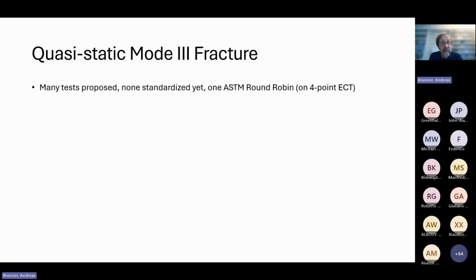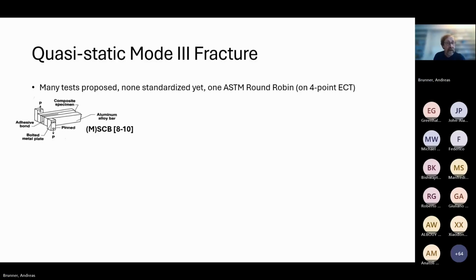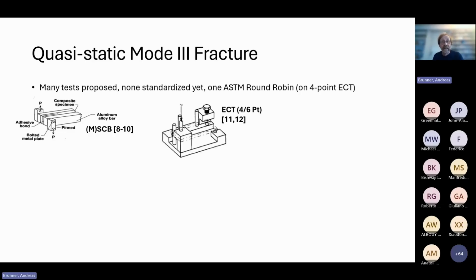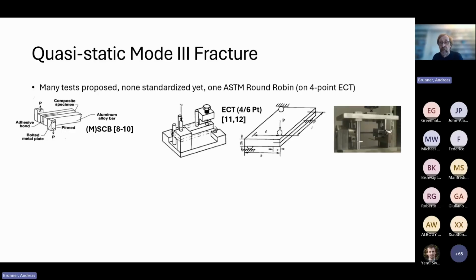Now for quasi-static mode 3, it has already been said as well that there's no standard. There was an ASTM round robin performed in the early 1990s, which used the 4-point edge crack torsion test, but this never led to standardization, and no one has picked up that as far as I know. Okay, there was the split cantilever beam, or there's also a modified version of that. The references are given on the last slides then, where you can look it up. Then this is the edge crack torsion, the 4-point version in the schematic here, and a photograph of the 6-point version that has also been developed.